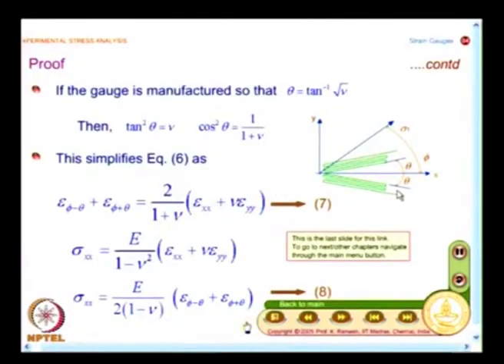And what we have seen, I have two elements, these are joined, and when you connect this in one arm of the Wheatstone bridge, I essentially measure the sum of these strains. And now I have an expression to find out the normal stress sigma xx directly from strain measurement. So, I call it a stress gauge, only the multiplication factor has to be reset in your instrumentation system. So, if you design a foil like this having two elements, when you make the measurement, it is possible for you to find out the normal stress component along the bisector.